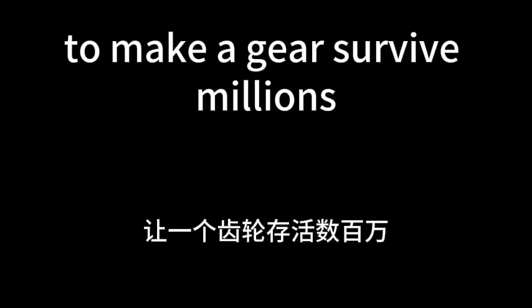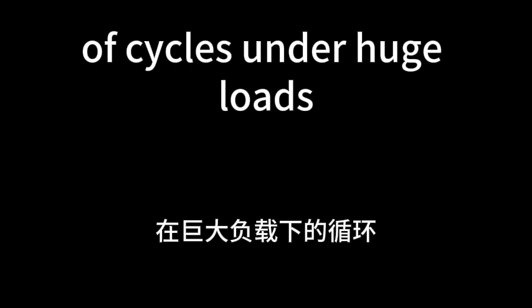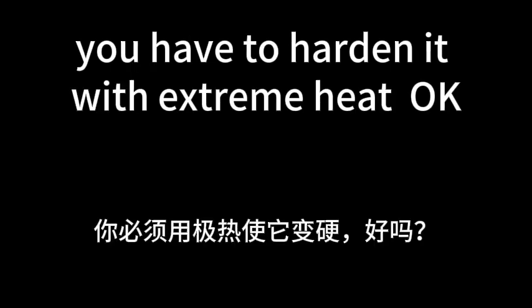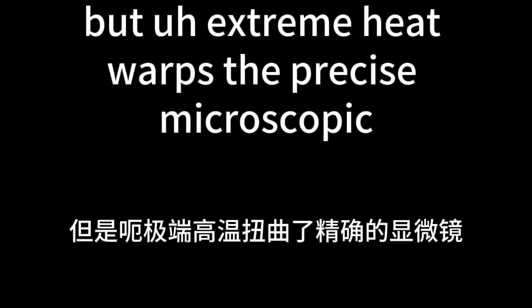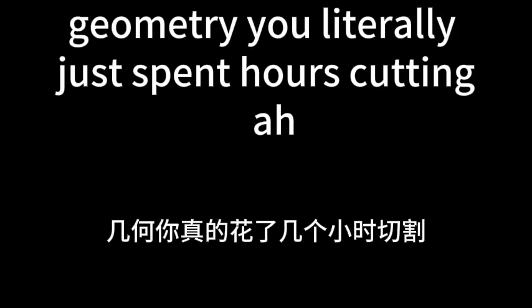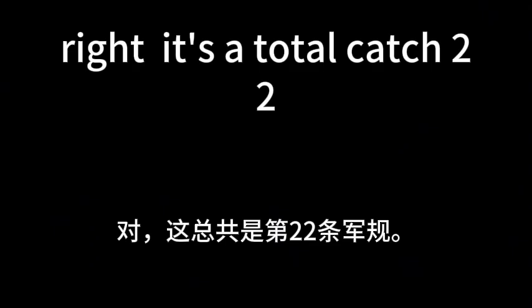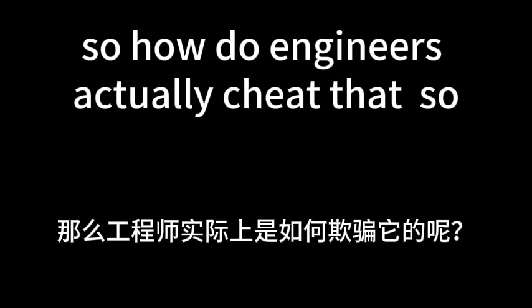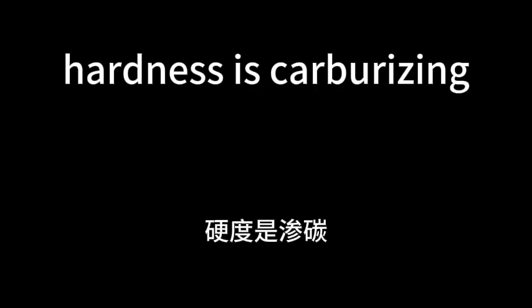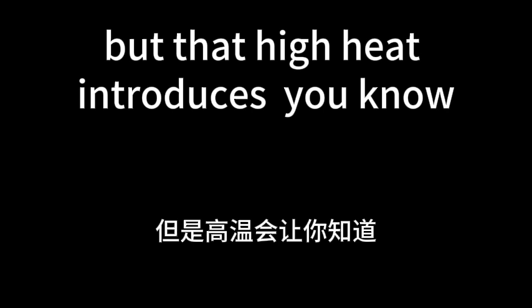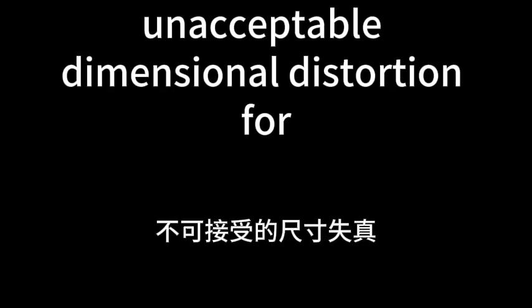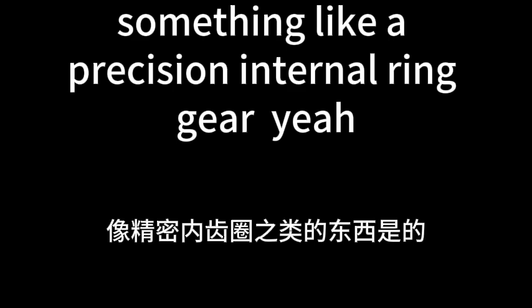To make a gear survive millions of cycles under huge loads, you have to harden it with extreme heat. Okay, makes sense. But extreme heat warps the precise microscopic geometry you literally just spent hours cutting. Ah, right. It's a total catch-22. So how do engineers actually cheat that? So the classic solution to surface hardness is carburizing. But that high heat introduces unacceptable dimensional distortion for something like a precision internal ring gear.